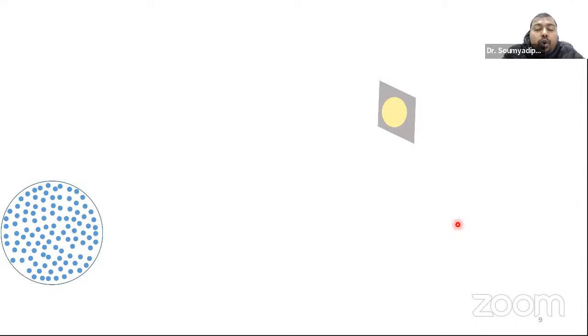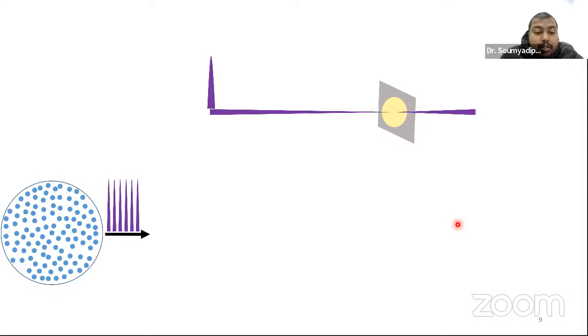Okay, let's go to transient absorption. When we have a sample, what we do is put the sample in a rotating cell, because we are going to excite it with pulsed lasers. So what happens first? We excite the sample with very short, high energy pulses. Those are femtosecond pulses. So what happens?